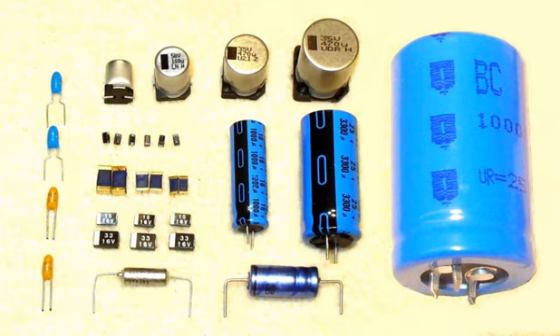The main causes of DCL for solid tantalum capacitors include electrical breakdown of the dielectric, conductive paths due to impurities or poor anodization, bypassing of dielectric due to excess manganese dioxide, to moisture paths, or to cathode conductors, carbon, silver. This normal leakage current in solid electrolyte capacitors cannot be reduced by healing, because under normal conditions solid electrolytes cannot provide oxygen for forming processes. This statement should not be confused with the self-healing process during field crystallization. See below. Reliability, failure rate.